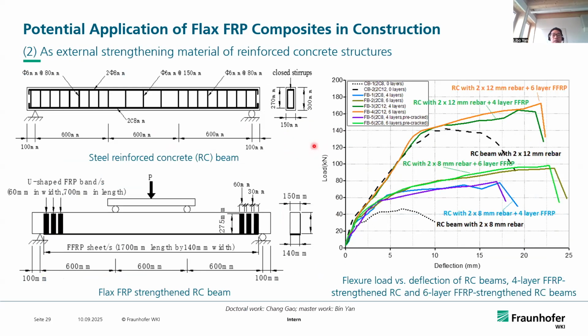Another application of the flax FRP is as the external strengthening material of existing reinforced concrete structures. So we used the U-shape and the L-shape flax FRP sheet to reinforce the concrete beams. As you can see in the load and deflection curve, compared with the reinforced concrete beam, the use of 4-layer or 6-layer flax FRP is able to increase the load carrying capacity, the ductility, and the energy absorption capacity significantly.